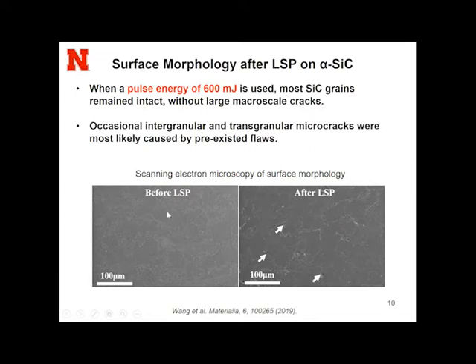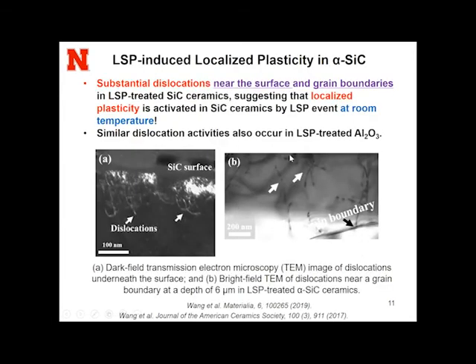silicon carbide. And here shows the surface morphology of the sample before LaserShock peening and after LaserShock peening. With this energy, we only see very tiny and very few microcracks. Most of them are from pre-existing flaws. And the surprising result here is, similar to metal, we did TEM analysis of the cross section. We found that near the surface and grain boundary, there's a significant amount of dislocation.